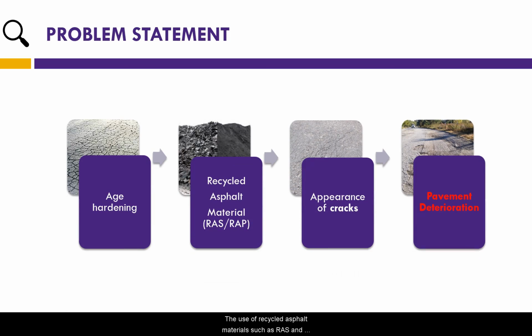The use of recycled asphalt materials such as RAS and RAP as a partial replacement for the virgin materials was introduced to reduce the use of virgin material and the negative environmental effects of asphalt pavement reconstruction. However, the main challenge with this alternative is that the asphalt binder in the recycled materials has been subjected to severe oxidation during service life. Application of the hardened and brittle asphalt binder in the construction of new pavement leads to an increase in the cracking susceptibility of the pavement and consequently affects the performance of the asphalt mixture adversely.